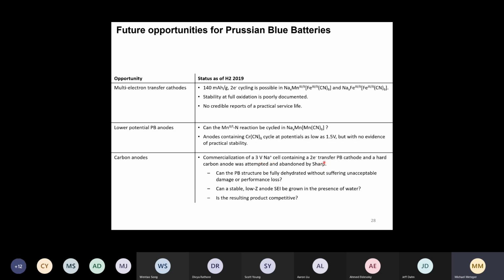Apparently this has been tried by Sharp, to use basically such a cathode as we see in the first row here, which would cycle 2 electrons per formula unit. And then you had a fairly large capacity, fairly high operating voltage cell, but it was abandoned. And there are still challenges. So we talked about this, either interstitial water or covalently bound water in the Prussian blue structure, which you want to get rid of if you want to use it as a battery material. If you go to very low voltages, I think we discussed this in last class also, the presence of water can be problematic.